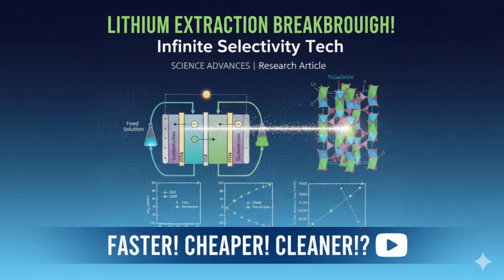And what about protons, hydrogen ions, H+, especially if the solution is acidic, low pH? Protons are actually an even bigger challenge in some ways. Unlike sodium or magnesium, protons can sometimes migrate through certain SSE lattices, including NASICON types, especially at low pH. So they can get past the bouncer? They sort of can, yes. They're very small and mobile. This means they can compete directly with lithium ions for transport pathways within the membrane, severely reducing the lithium flux and potentially impacting the overall efficiency and purity.